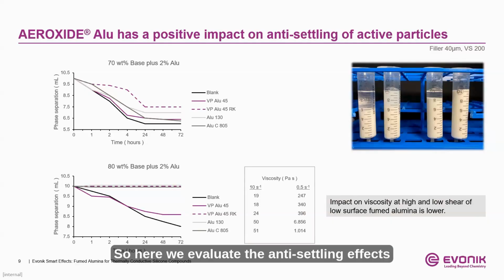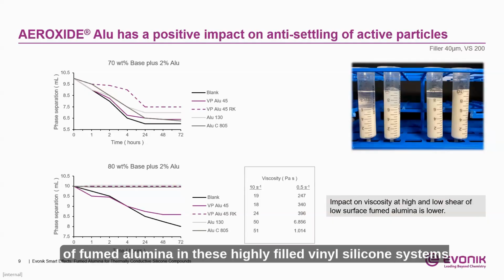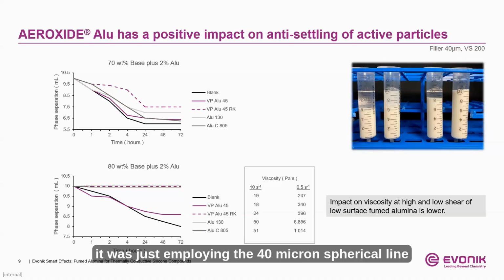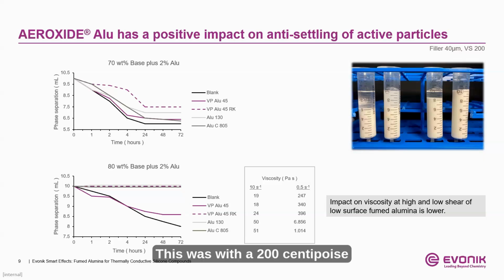So here we evaluate the anti-settling effects of fumed alumina in these highly filled vinyl silicone systems. Here it was just employing the 40 micron spherical alumina by itself as the main thermally conductive filler. This was not using a blend, and this was with a 200 centipoise vinyl silicone material. The test is fairly straightforward. You can see it there on the right.